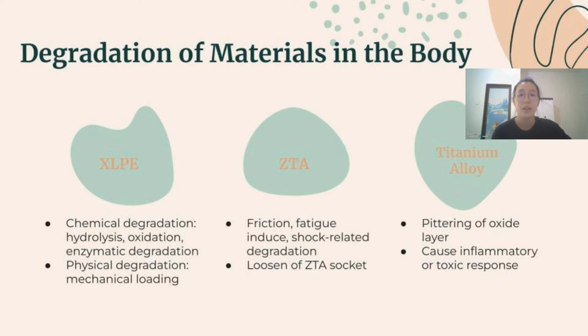For the ZTA, which makes the liner and the femoral head, friction and fatigue-induced and shock-related degradation may exist. According to the studies, the ZTA component is subjected to wear, shocks, and mechanical loading. The elastic imbalance between ceramic materials and bone can cause ZTA sockets to loosen. This results in the degradation of the femoral stem as well. Besides, shock-related degradation due to shocks increases wear that triggers low temperature degradation, which increases wear as well.